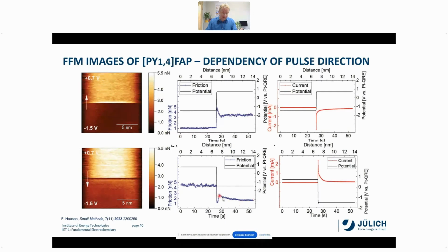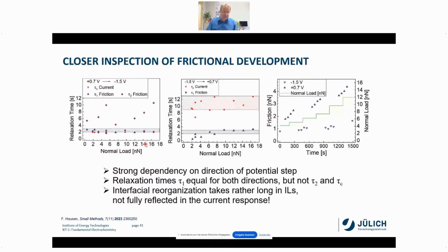So from this, we can now calculate all these different numbers, and then we can get information on how long we need to have a real stabilization at this interface, which is, of course, really important if you use ionic liquids in energy materials, so that you get a stable interface again. And then you see that these relaxation times change drastically. The capacitive current is rather fast when we switch from positive to negative, but gets much slower if we switch to the other direction. And friction behaves also drastically different here. So we have a strong dependency on the direction of the potential step.